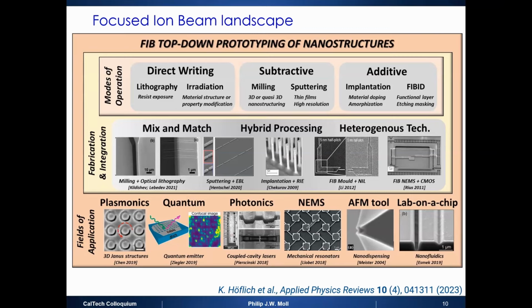It's a beam of ions, really that simple, and you focus it on your sample. So what you can do is work in subtractive mode. You etch away your material locally. You can also work in additive mode, where with a gas injection system you put in some gases that adsorb, and then you can deposit things. So you can deposit superconducting materials, insulators, and metals, and thereby build up heterostructures. And you can also do lithographic direct writing or implantation, which are very interesting fields that our friends in quantum computing exploit quite a bit.